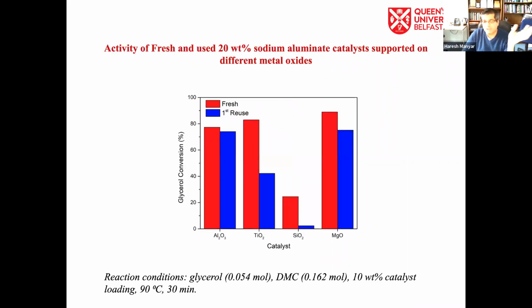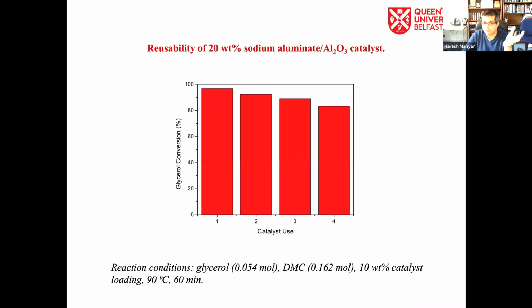We tried many different metal oxides like titania, silicon oxide, magnesium oxide, but aluminum oxide, alumina, was the most robust material which we found. In terms of recyclability, it was also good. A decent recyclability study was up to 4 recycles. We could reuse and recycle this material. It's a cheap material, not very expensive. And we can really use it easily if we prepare it by mechanochemical methods.